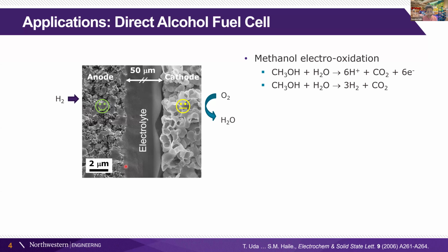Because our anode is so good, we can do more interesting things than just simply providing hydrogen. And we can, for example, use this in a direct alcohol fuel cell. And methanol, for example, I've shown you here the way that you can use methanol in a fuel cell that has a proton conducting electrolyte. You generate the protons by reacting the methanol with steam, either directly in an electrooxidation reaction or by having a steam reforming reaction that produces hydrogen and CO2, and then the hydrogen gets electrooxidized at the anode side. Both of these, of course, produce CO2 as products, which we don't want to have.